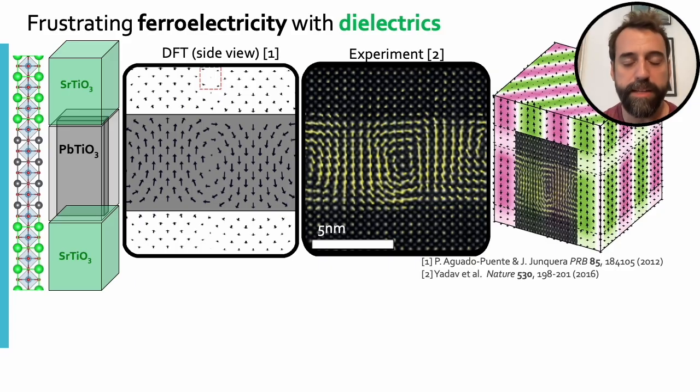So without going into details, let me just mention that this kind of methodology relies on writing down the energy of a given compound as a Taylor expansion around a reference structure. And we write this Taylor series as a function of atomic and strain degrees of freedom. Now, the coefficients of this series can be fitted to first principles data, and the resulting model can be made arbitrarily accurate by increasing the length or the order of this Taylor series.